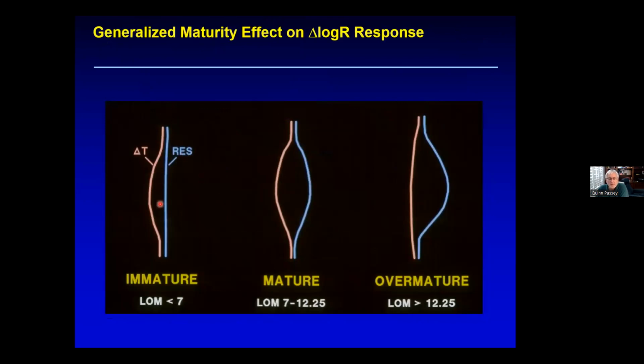So the rule of thumb is, when it's immature, we get a sonic component in the shale because of the low velocity, or long transit time, of the kerogen. The resistivity, though, is flat. When it's mature, you get both sides of this. And when we go to over mature into the shale gas realm, you still get some porosity log response, but usually it's in the resistivity.